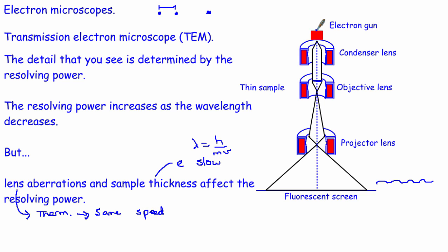When some of them are emitted from the metal, some might have a very small amount of kinetic energy to start with, because they came from the surface of the metal, whereas electrons deeper inside the metal would need more energy to get out, like the photoelectric effect. So although you're providing the same amount of energy to both electrons, this electron will have a smaller kinetic energy than that one. They should have the same speed, but they don't.